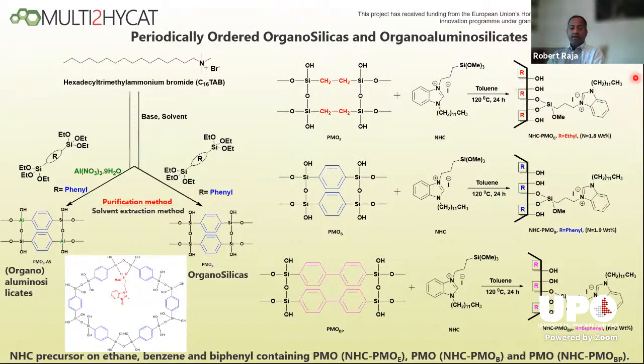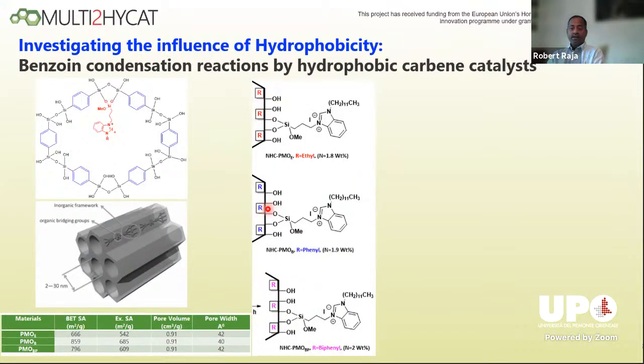So now you have this organocatalyst, this benzimidazole catalyst, which from the previous slide was attached to a hierarchical structure, which was mostly hydrophilic in nature. We can now start to impart different degrees of hydrophobicity within this particular material type. So these periodically ordered mesoporous silicas also have these enhanced pore apertures. You have this pore aperture of about 40 angstrom there, which can help with the mass transport and diffusion. And they have reasonable surface areas compared to zeolites, which means one can get quite good catalytic rates and turnovers.